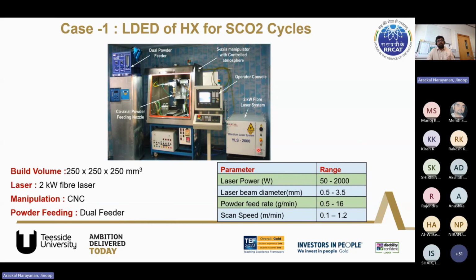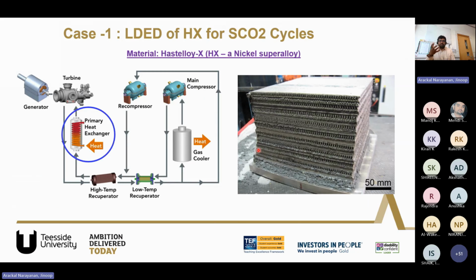So we used a 250 by 250 by 250 system with a 2 kilowatt fiber laser with CNC manipulation and a dual powder feeder. So this was the application. We wanted to develop a heat exchanger that can be used as a primary heat exchanger, which can take the heat from the nuclear side, from the energy side, and then transfer it to the power generation side. So the material that was identified for this was Hastelloy X.